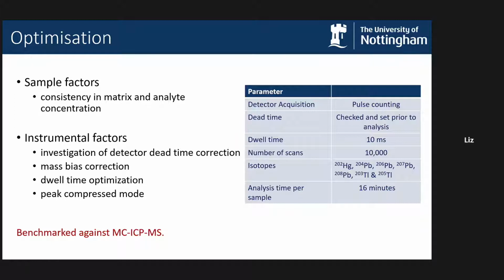We also had to do a mass bias correction. So first we took our lead isotope ratios and we corrected them for any interference on the lead-204 signal from the mercury-204 signal, and operational blanks we used as well. The data that we then got, we corrected for mass bias, so different masses of the isotopes, using both proxy internal and external standards.